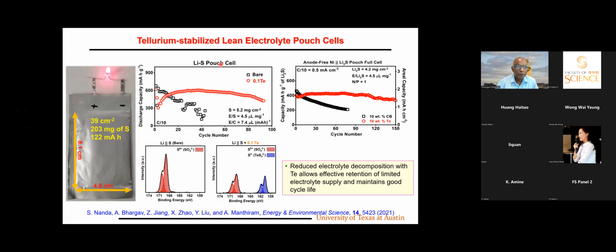So this is the Li-S pouch cell with lithium metal on the anode side. This is the anode-free cell with the Li2S and pouch cell. You can see in both cases the tellurium addition. This is anode-free, amazing. It gives much better cyclability, but the capacity is lower. This is per gram of Li2S, not sulfur. And also, we have not added any catalyst here. So, add catalyst, electrocatalyst, then it helps the redox reaction, the capacity will still go up.